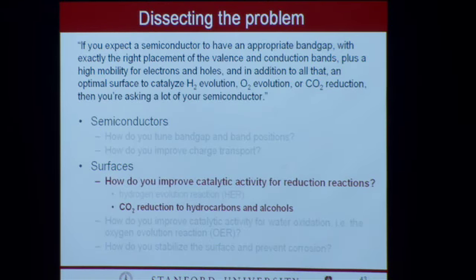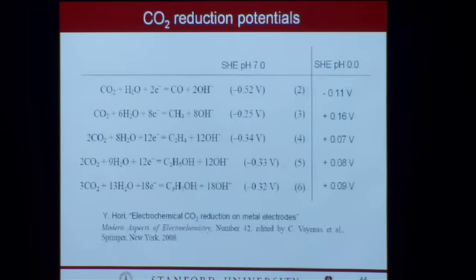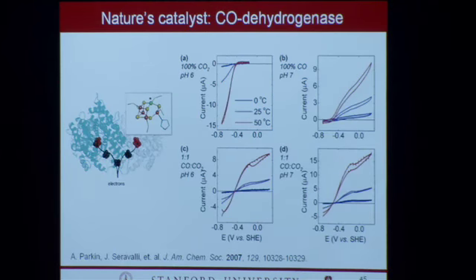I'm going to take just 2 minutes to finish up some work we've done on CO2 reduction. And one of the big points that I tried to make earlier is that if we look at the equilibrium potentials for CO2 reduction to different molecules you might be interested in making, say ethanol, ethylene, methane, et cetera, these potentials are very close to zero, which is what the hydrogen evolution potential is. So that's why I was saying thermodynamically, it's not too much more difficult to reduce CO2 than it is to evolve H2. It's the kinetics that are the problem.